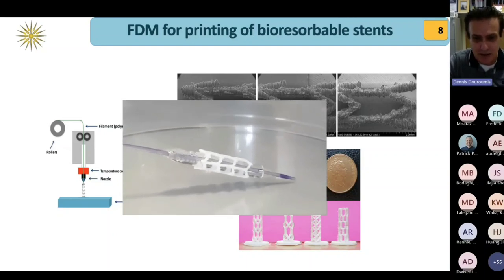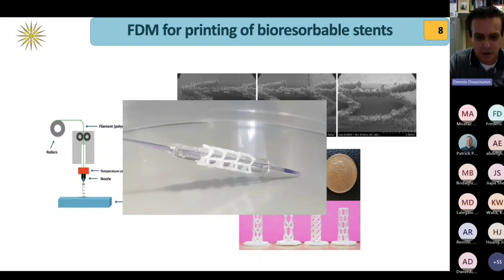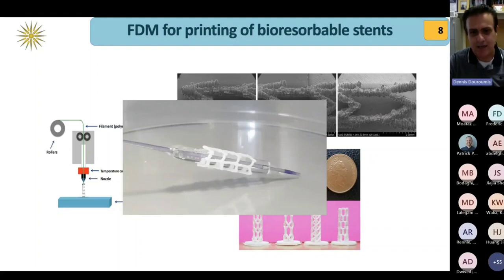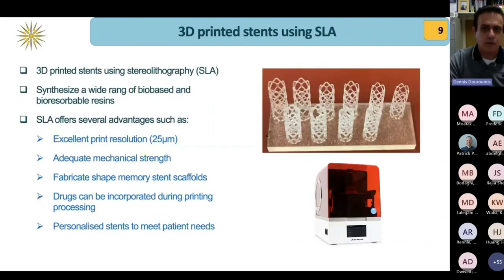However, as I mentioned, the major problem we had was that, due to technology limitations, we couldn't take down the thickness of the stent below 300 micrometers. And we know from the metal stents that it has to be at least 150, or let's say around 200 micrometers. So we then moved to a different technology. Probably you're aware of that. It's called stereolithography. And then we started working on our design. We started designing our own resins by trying to use bio-based and bioresorbable materials.